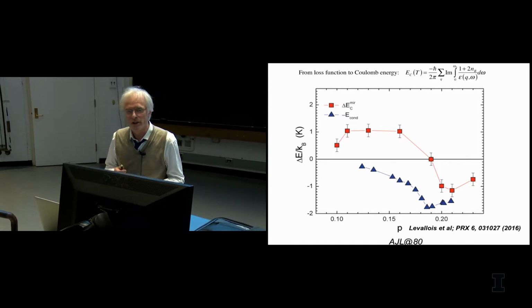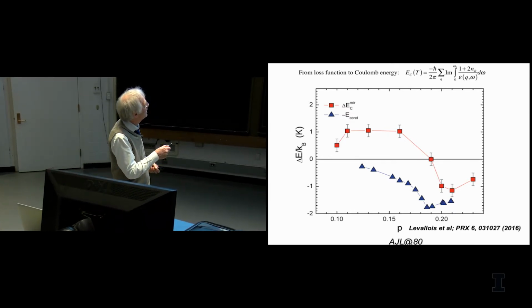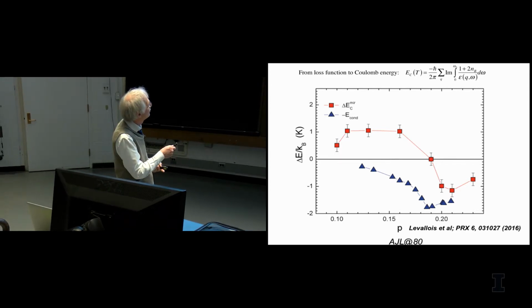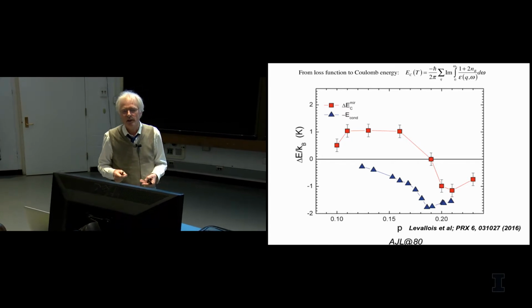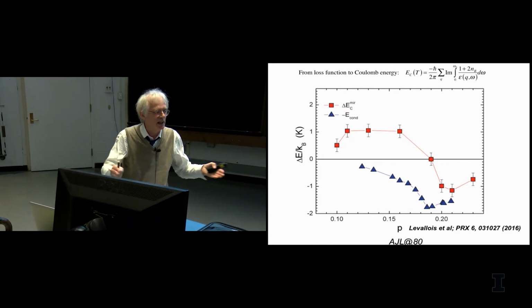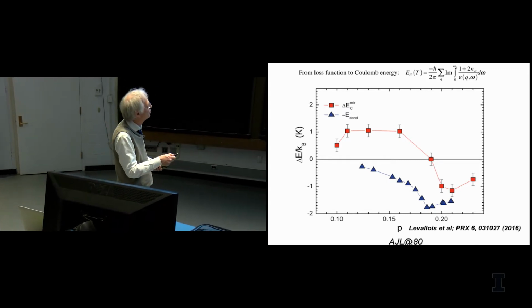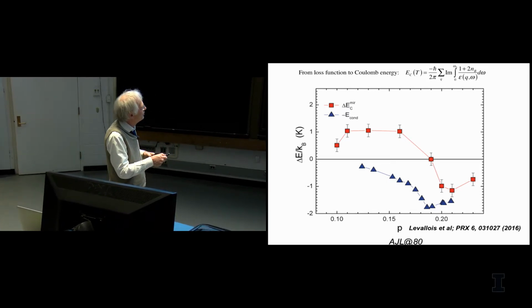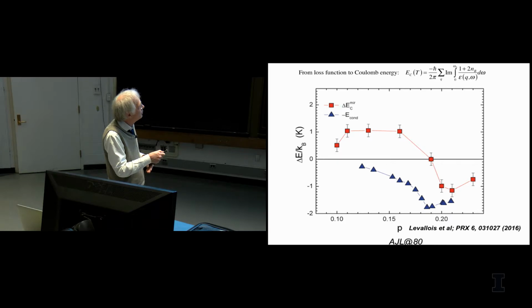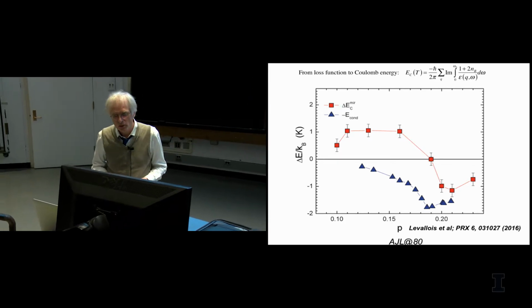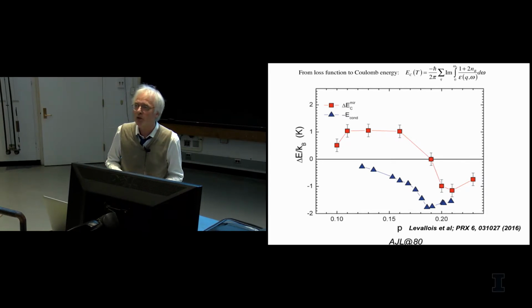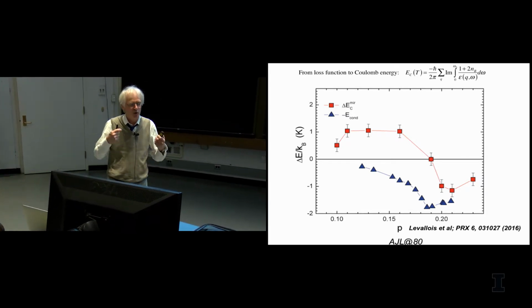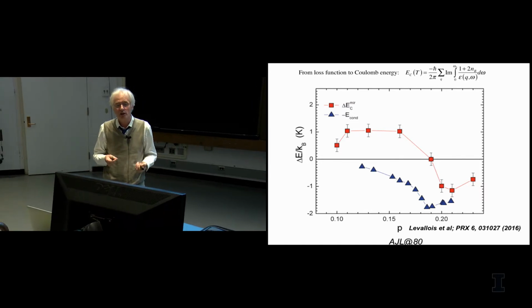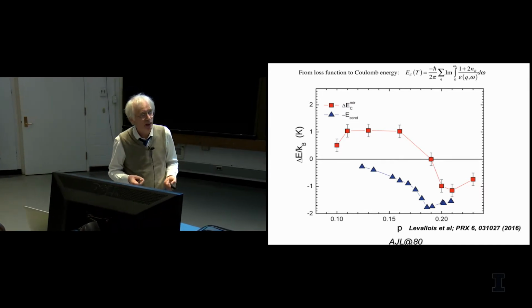But there's also a lot of hope in here. We are not looking at numbers here which are ridiculously different from what you find from this condensation energy. It's not a factor of 400 smaller, nor is it a factor of 400 bigger. So we are in the right ballpark. Given the somewhat crude assumption that we made about how it actually depends on k-space, you could easily imagine this to be a factor of 2 larger, but also smaller, even within that model. And it is easy to imagine that with these kinds of numbers, by actually collecting all momentum information, you would find something that agrees with the experiment. Of course, it's also true with this model that it cannot be wrong. If you take all momentum values and all energy values, in the end, you should get precisely the same result as for the condensation energy.